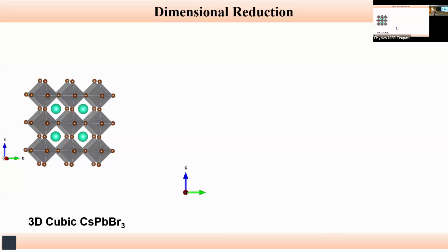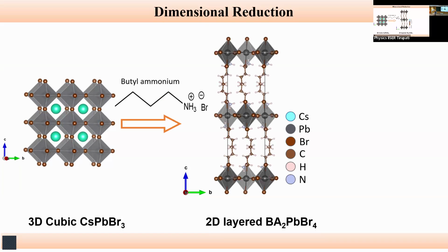But if you bring in a molecule which has a tremendous affinity to hold hands with this inorganic unit, even without room enough, what that will do, like a butyl ammonium instead of a methyl ammonium, because methyl is smaller and the butyl group is much larger. Methyl ammonium would have been just this much. Butyl ammonium is this much. What it does is actually split it open like this to accommodate the long length between. So it cuts along this line. It's a two-dimensional connectivity. Now these octahedra are connected along this direction and the perpendicular direction. In this direction, you see there's no connectivity. So this is now a two-dimensional structure, derived from the three-dimensional structure because I've put this in.